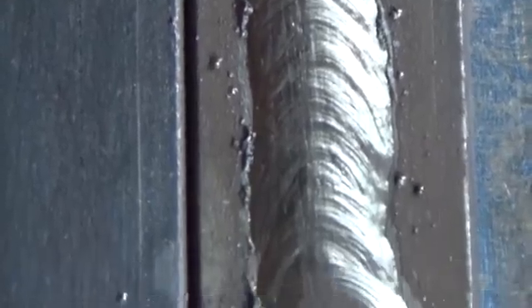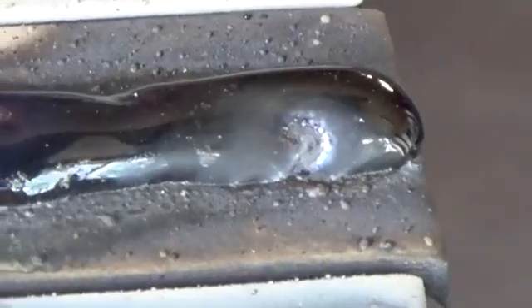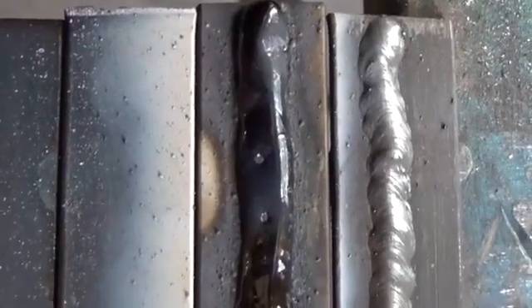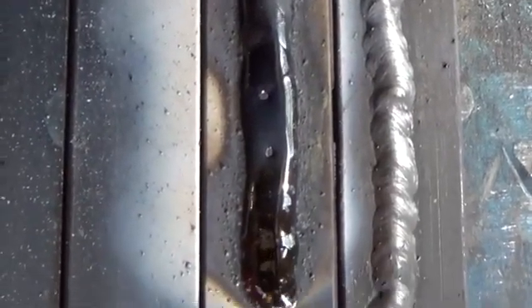We turn to welding with the basic coated electrode special. The first weld, electrode positive, current is 50 amperes. Please note, the burning of the arc is not very bright. Metal spreads poorly. The weld has a rather narrow and high shape. Note that even the appearance of the slag differs from the slag with the rutile electrodes. This slag is denser and more fragile, and is cleaned off much more difficultly. This requires much more time to clean up the weld.